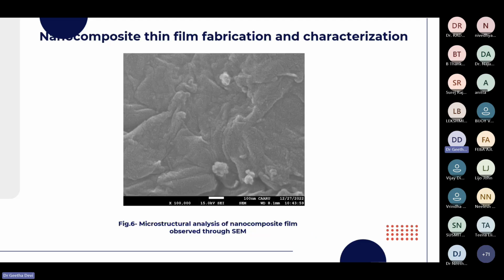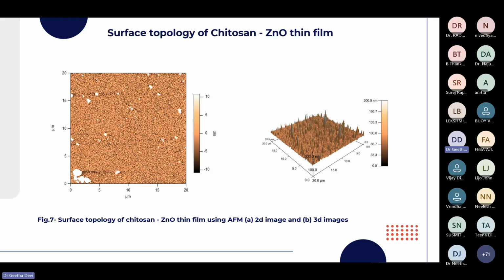And the surface morphology of the coated thin film is observed through scanning electron microscopy. It is seen that the coating is well formed, and also we investigated the surface topology, how the surface looks like at the atomic level. We can see that this is a two-dimensional figure and the other one is a three-dimensional image using atomic force microscopy.